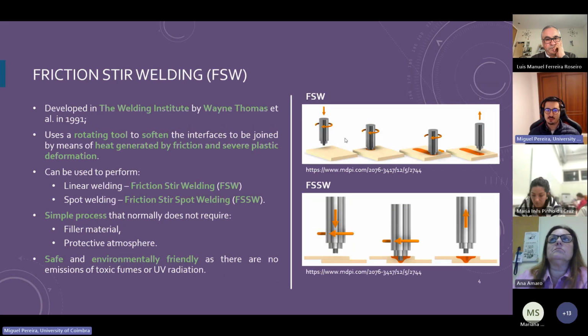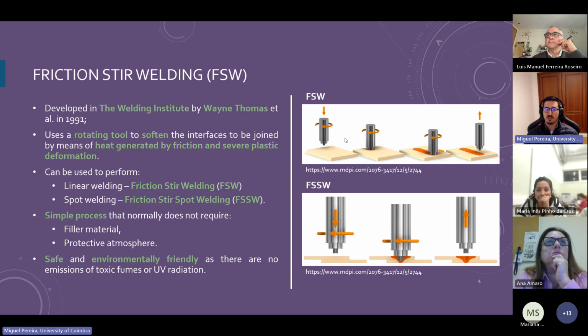Friction stir welding was developed at The Welding Institute by Wayne Thomas and his colleagues in 1991. It uses a rotating tool, as shown in the images on the right, which softens the interfaces to be joined by means of heat generated by friction and severe plastic deformation. We can perform linear welding, which is the conventional friction stir welding, or spot welding, which is the process we use, friction stir spot welding. It is considered a simple process that normally does not require a filler material or a protected atmosphere, and is also considered safe and environmentally friendly, as there are no emissions of toxic fumes or UV radiation.